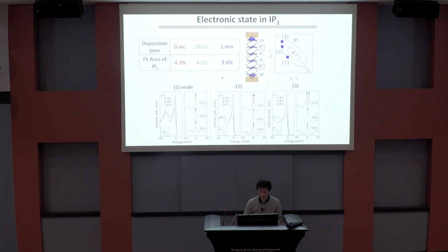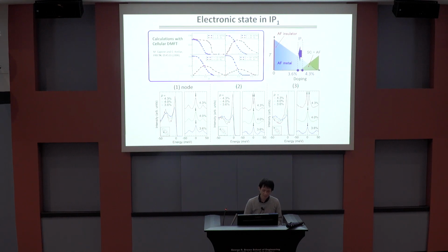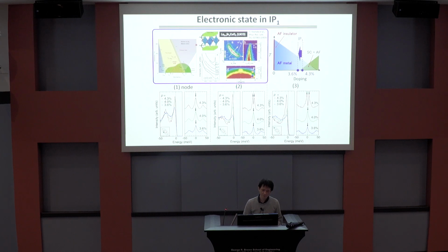We found that the superconducting gap, clearly observed before potassium deposition, is crossed out by 1 minute of potassium deposition, and this doping level is around 4%. So I can also draw the edge of this dome. This dome ends around 4%, which is kind of surprising, because some calculations suggest only a tiny carrier concentration can create pair formation, but 4% is some kind of magic number. So this is consistent with that of the very dirty case of LCO.